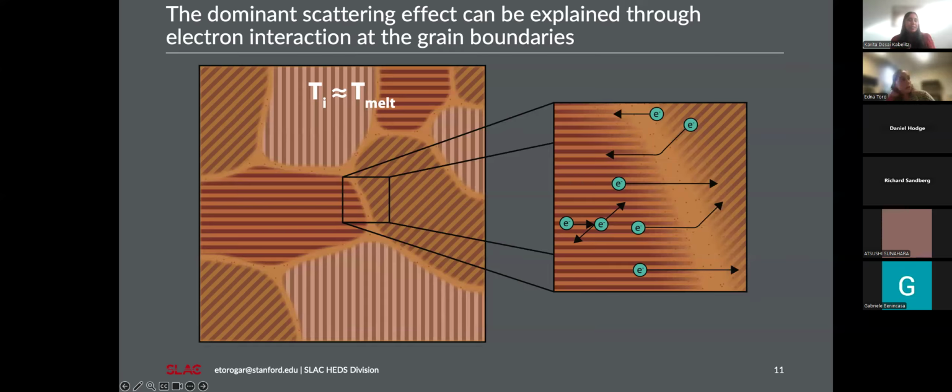So I guess we had some problems regarding the quality. Not going into a specific deposition, there was a time where the conductivity measurements were not making a lot of sense. So I had to learn how to grab these sample films and measure what the thickness was. What ended up happening is that an error of even 10 nanometers will give us a completely different result.